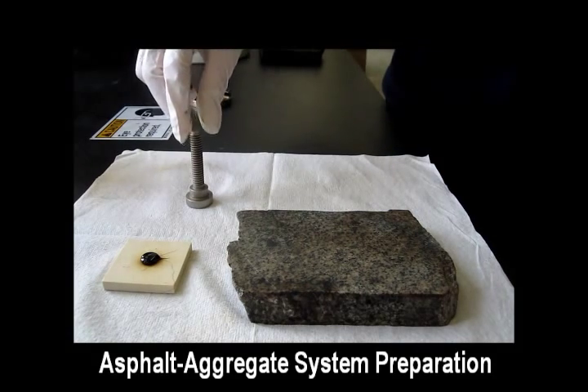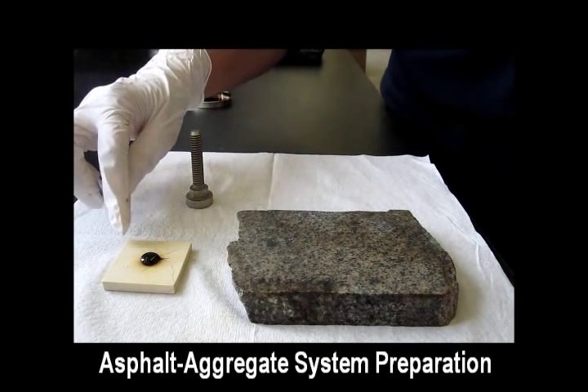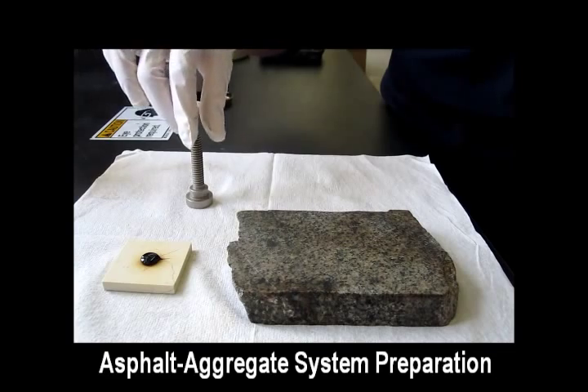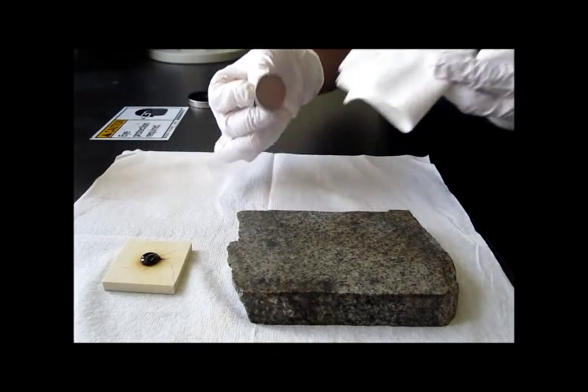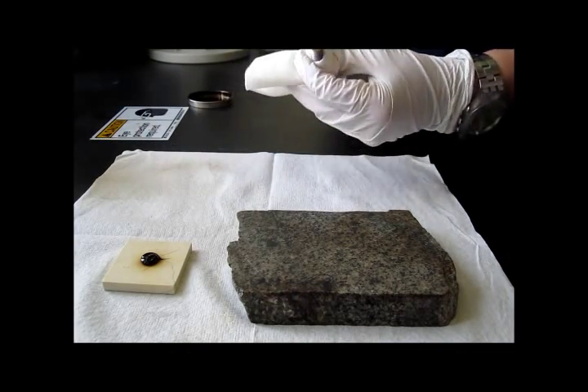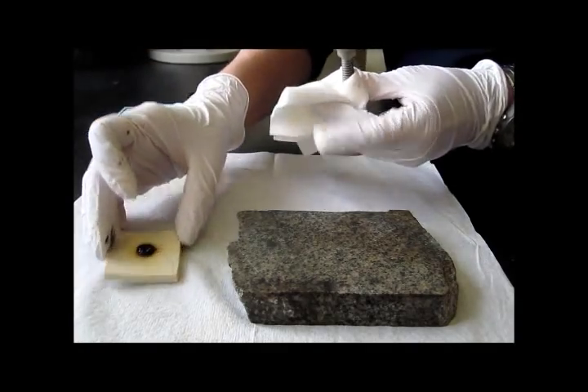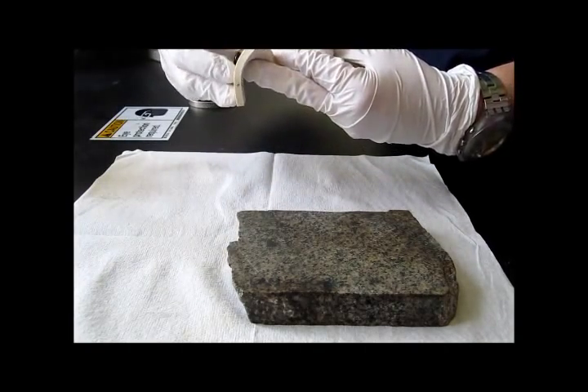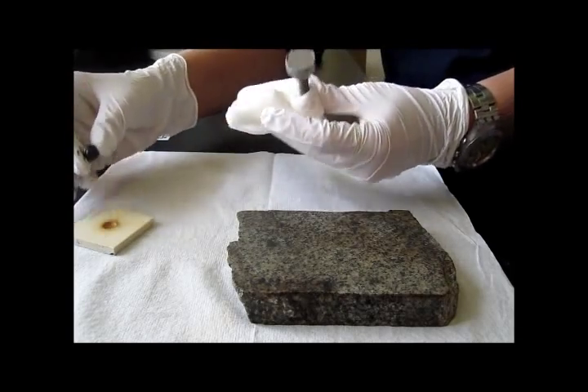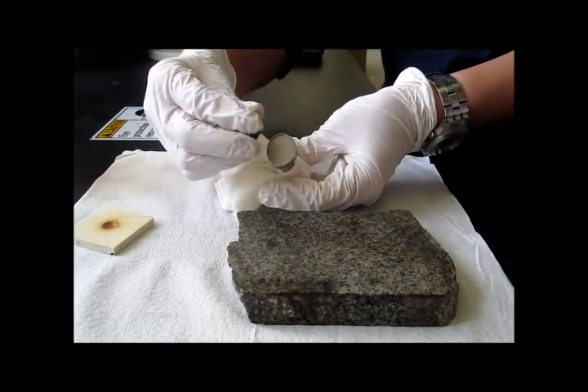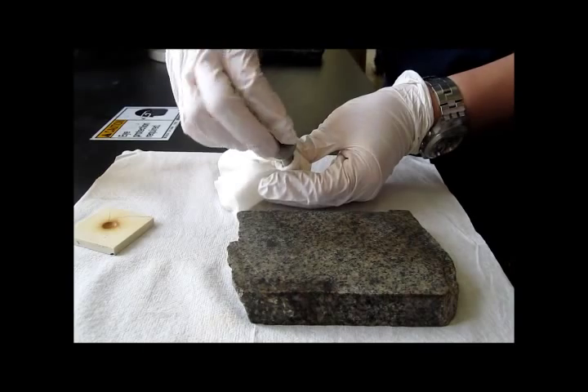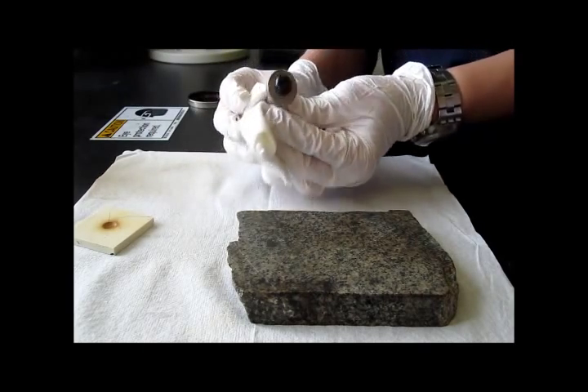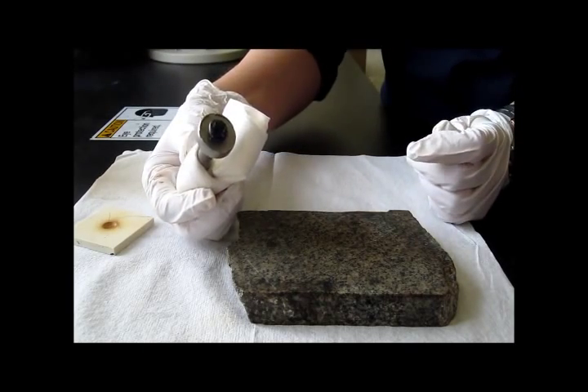The stubs are removed from the oven and an asphalt binder sample is placed immediately on the surface of the stub for approximately 10 seconds. Then the aggregate plate is removed from the oven and the stub with the asphalt sample is pressed into the aggregate surface firmly until the stub reaches the surface and no excess asphalt binder is observed to be flowing.